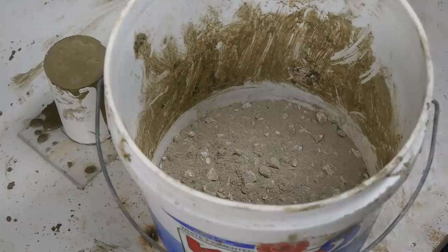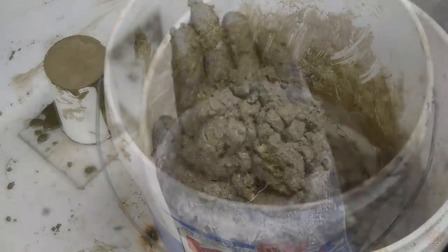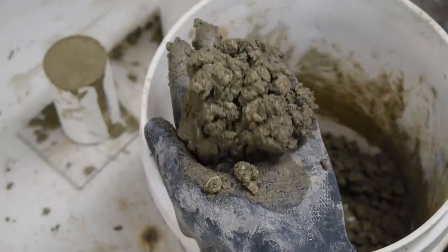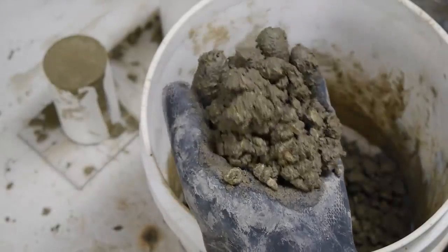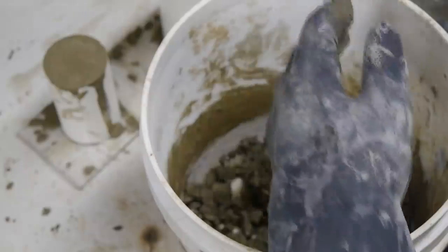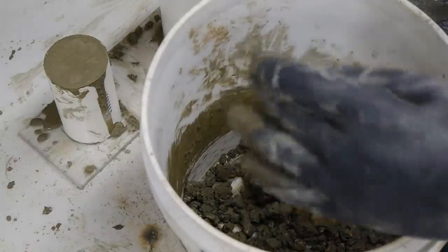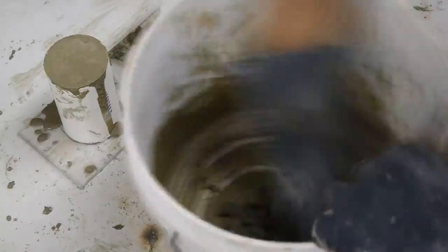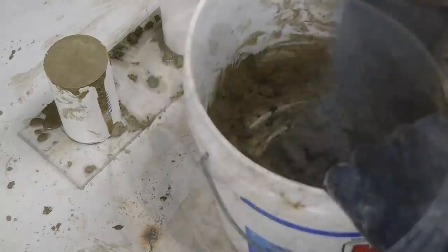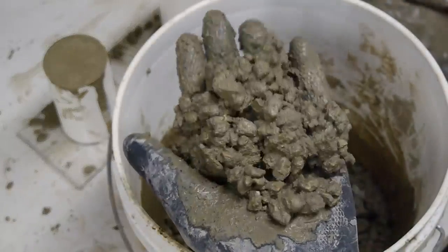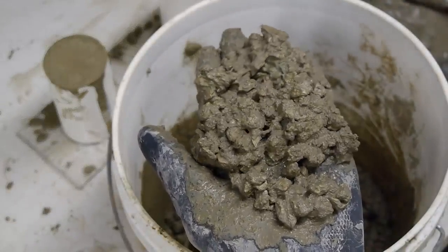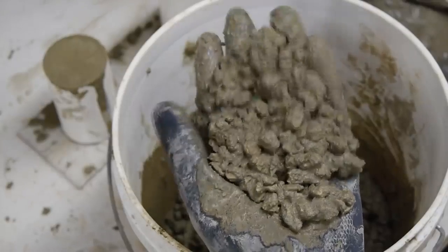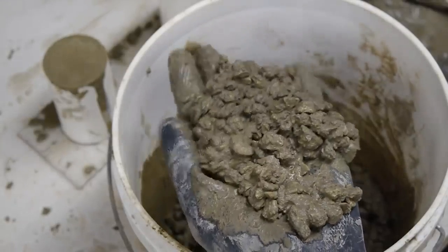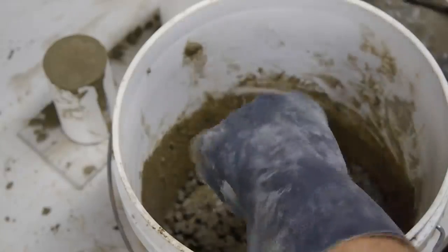For this final batch, I used the exact same amount of water as the previous mix. You can see it doesn't flow at all. It would be impossible to use this in any complicated formwork or around reinforcement. But watch what happens when I add the superplasticizer. Just a tiny amount of this powder is all it takes, and all of a sudden, the concrete flows easily in my hand. In many cases, you can get a workable concrete mix with 25% less water using chemical admixtures.